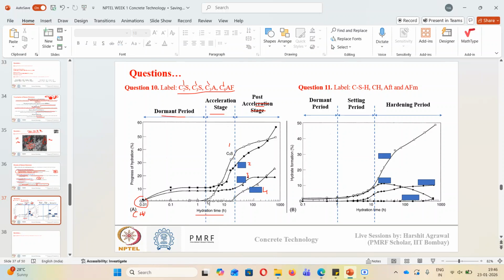We have seen that C3S starts to show reaction at the end of the dormant period. You can call this the pre-induction period or dormant period also. In the acceleration stage, C3S starts to convert into CSH as the osmotic layer pressure rises and the semi-permeable membrane breaks, and over time it slows down.